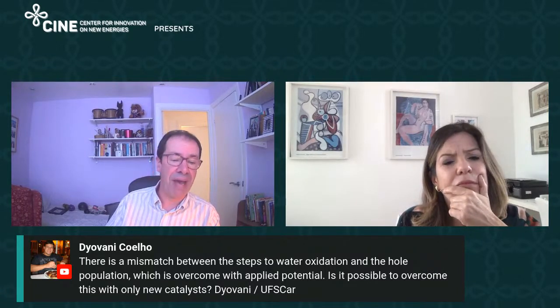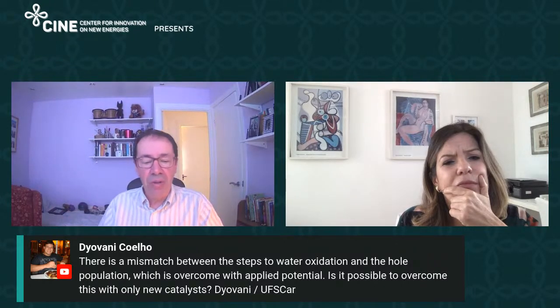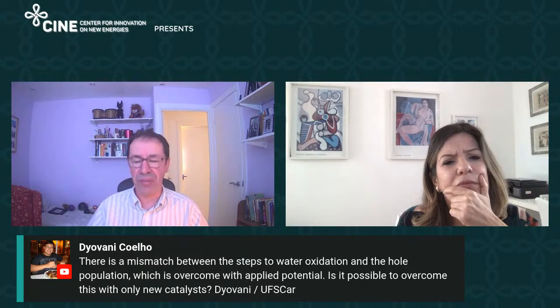And that does beg the question of why do you want to put catalysts on? And of course, the reason why hematite can oxidize water, or one of the reasons why it can oxidize water without a barrier, is because the valence band is so deep. And so these holes are effectively operating at a huge overpotential, because any hole on the surface of hematite is very deep in a deep valence band. Most catalysts work at much more modest potentials, and so are thermodynamically more efficient.